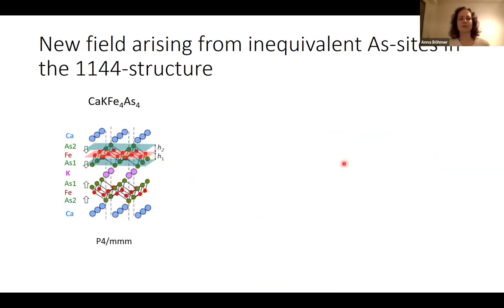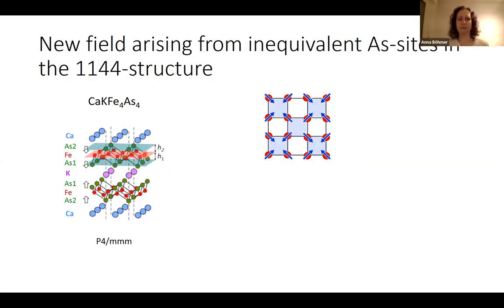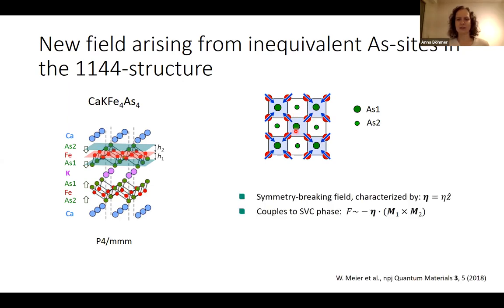And where does the 1144 structure come in here? If we look at the two distinct arsenic sites and the iron plane, I put again the magnetic structure, and now I add the arsenic atoms. They are symmetry inequivalent, they're distinct. So now this provides some sort of field. That field must be aligned along the z-axis and also has some staggered symmetry. So every other iron plaquette, there's a different arsenic site. So it really turns out that this causes a symmetry breaking field that couples bilinearly to the spin vorticity, the cross product of these two magnetic order parameters.